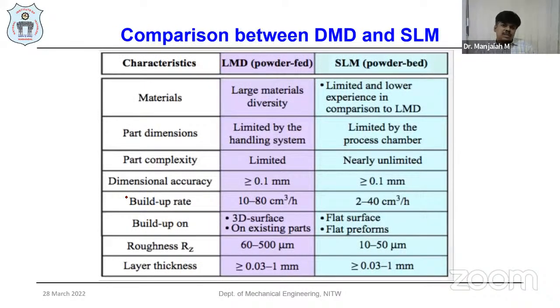Just a brief comparison with respect to DMD and SLM, powder bed fusion and direct powder feeding technology. The part dimensions are limited by the handling systems in laser metal deposition or DMD systems, but are limited by the chamber in SLM systems. Part complexity is limited in DMD, but there is no limit in part complexity in SLM systems. In both machines we get good dimensional accuracy, and the build rate is very good in DMD compared to the SLM process. Any 3D surfaces can be edited, repaired, or have features added on any existing parts with DMD. But we have to go with only flat surfaces for the SLM process.